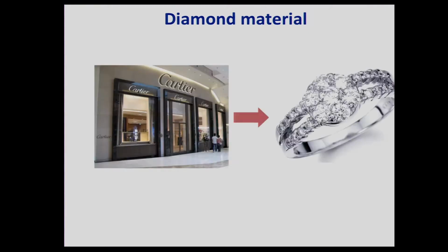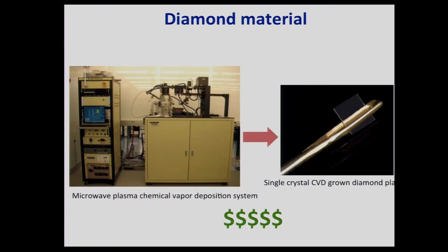One way in which my group is focusing on this is through the creation of the material. So there are several ways to get diamond. One could go to Cartier and spend a lot of money on such a diamond, or you could spend even more money actually and buy one of these. It's called a CVD, a chemical vapor deposition system, and this was a diamond growth system that was purchased by David Awschalom and really set up by his students when he was at UCSB. As I already mentioned, he's since left. But the idea here is that you can grow very clean diamond with very good control. It's a bit slow, 8 nanometers per hour, so we only grow about 100 nanometers of diamond, but we grow that on top of a clean substrate of diamond, and we really only care about that last 100 nanometers.